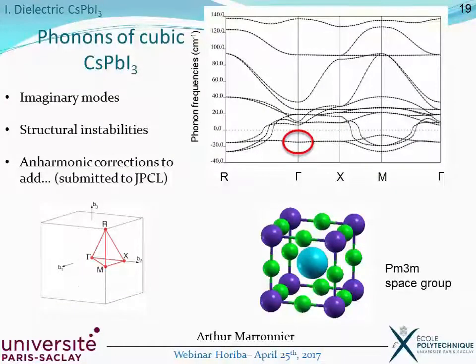So I won't go too much into detail about the phonon results that we have, but just to give you one example for the cubic phase, here on the top right you see the phonon frequencies. You have 15 modes because you have 5 atoms and 3 directions. But one remarkable thing is that we found some negative modes, some structural instability at gamma, at the center of the cubic lattice. And this is the sign of anharmonic behavior. So we had to add some anharmonic corrections to our values of the dielectric constant. I won't give too much detail on this, but this is the work I've done after working on ellipsometry and dielectric properties, and this was submitted last month to JPCL.